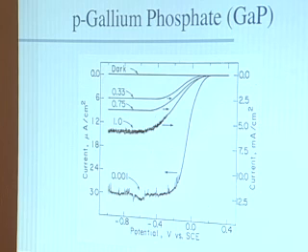Why is that? Because other ugly things start to happen when you go to higher intensity. You run into both kinetic limitations and decomposition of the semiconductor. So what you should be taking away from all of this is a very simple idea. You can use a large band gap semiconductor, such as a metal oxide, and you can split water just fine with a quantum yield at least approaching 1, if not 1.